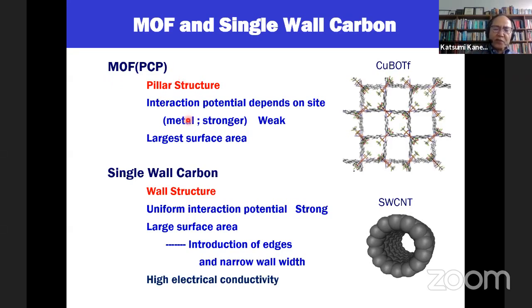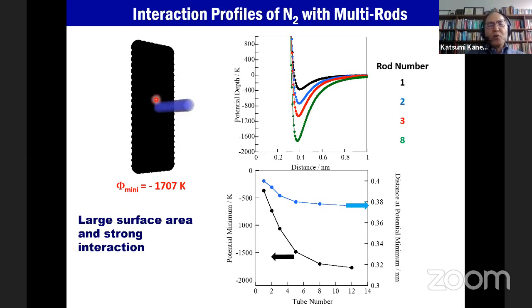If you want to get a larger surface area, of course, MOF has the merit of a high surface area, such as 3,000 square meters per gram, because the one-dimensional structure is a frame. But for example, here I will show you single wall carbon nanotubes. In this case, of course, the surface area is large, but not so much as the MOF. But MOF, basically, don't have strong interaction potential because the wall is very, very narrow. Here, I will show you the reason.